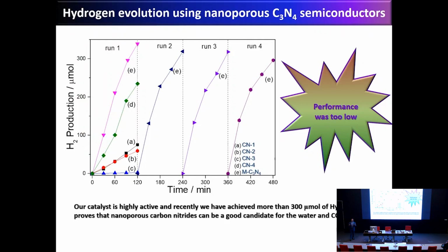But is that enough for the commercialization? No, it's not even 0.1% of solar to hydrogen conversion efficiency if you really want it. And also it's normal water. So this may be mainly due to the fact that the band gap of the material is 2.7 electron volt and there is a fast electron hole recombination.